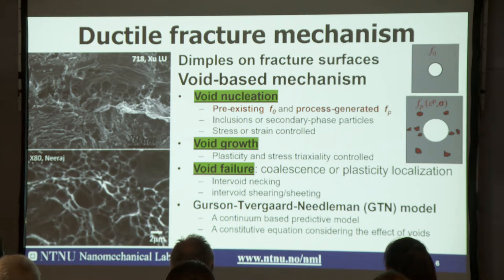Once the voids have nucleated, they will grow under plastic deformation. The growth certainly is dependent on the stress state, depends on the stress triaxiality. However, the void will not grow forever. Enough will be enough. So at a certain stage, void failure will occur.